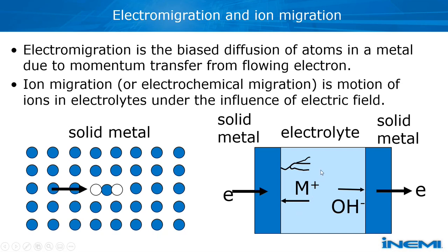So you could get what's called dendritic growth. So you can see this tree-like structure forming. So these dendrites can short circuit the metallization on a circuit board. So that's ion migration. So electromigration happens in metal, whereas ion migration happens in an electrolyte. So that's the big difference.